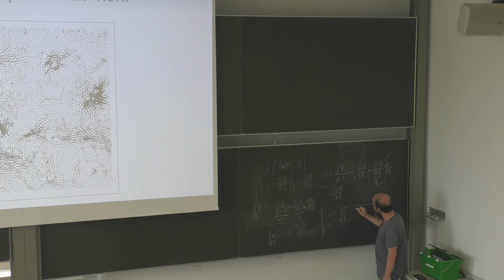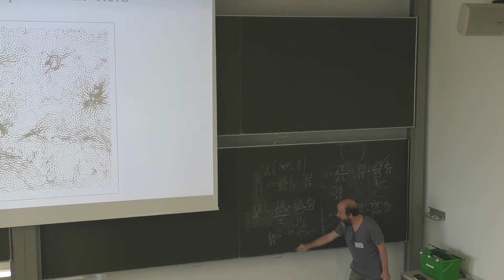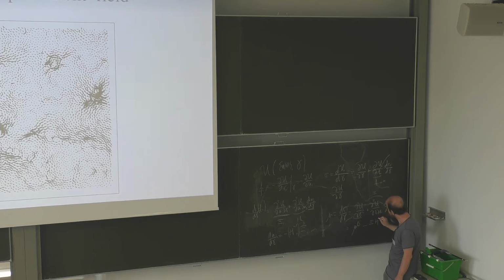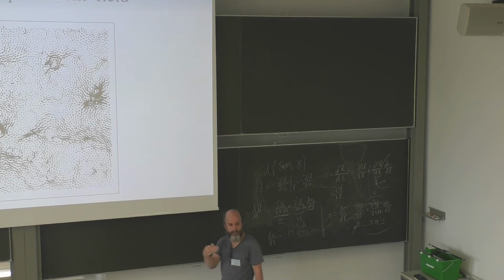And I play the same game. So now I derive stress, so I take the total derivative of that. So it's d²u/dγ² plus d²u/dγ dr times dr/dγ. So here we find, again, this psi field. Here we have the second derivative of the potential of phi. This is the Born modulus. This is the modulus you would get if you assume an affine response. And now you have a correction, and now you have dr/dγ. I plug that in, and this comes with a minus sign, psi H^-1 psi. And so you have a negative correction to the Born modulus, which comes from non-affinity.